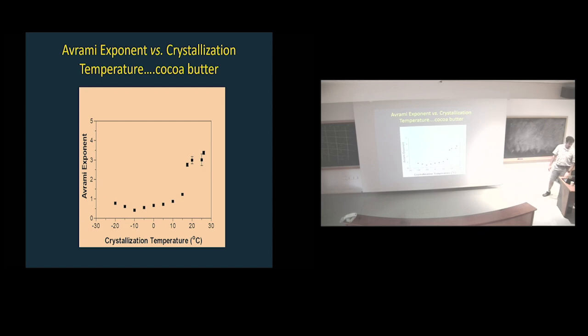Like no problemo. But in reality, you have two species, that something comes up maybe and something nucleates on that, so the story changes a little bit if you adopt multiple species. And that's, again, showing you how cocoa butter crystallizes isothermally at different temperatures. The Avrami exponent, how it changes for a more, that's actually pretty close, eh? Three-dimensional, and we all know that these are pretty needle-like. And look, that's around 1. Don't get too hung up on the fact that it's 0.8 versus 1.1, right? So it's around 1, and the other one is more like a three-dimensional growth.